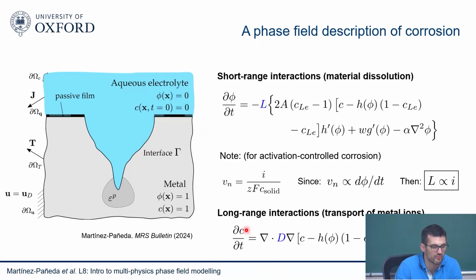We have the evolution of those metal ions as a function of some diffusivity. And this is good news because diffusivity we know. This is a variable that we can easily measure. We know it before we run calculations. And then the other thing that you have is, of course, so this is the conserved quantity, what people call the Cahn-Hilliard equation. And then what you have here is what people call the Allen-Cahn equation. So this is the phase field evolution equation that basically describes material dissolution. So the phase field is describing the interface between the electrolyte and the metal. It's describing the evolution of the corrosion front. So it's describing kind of the detachment of metal atoms from the interface.